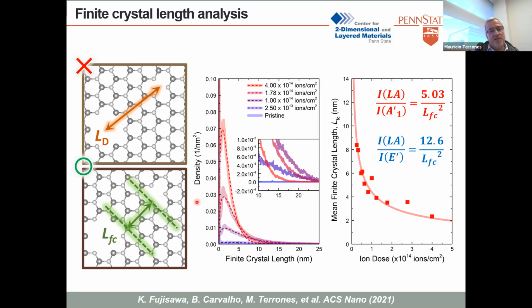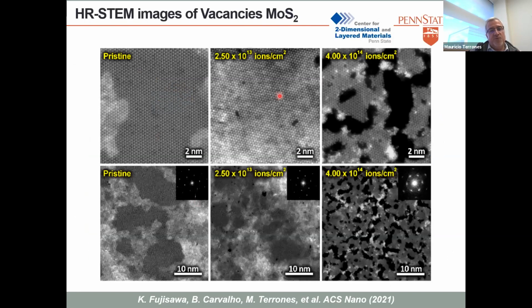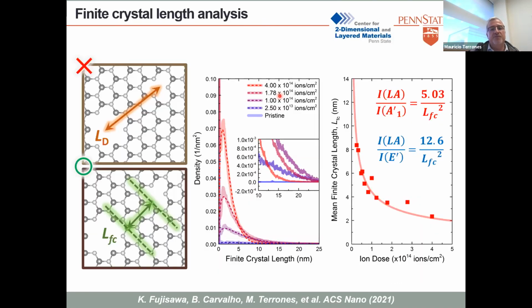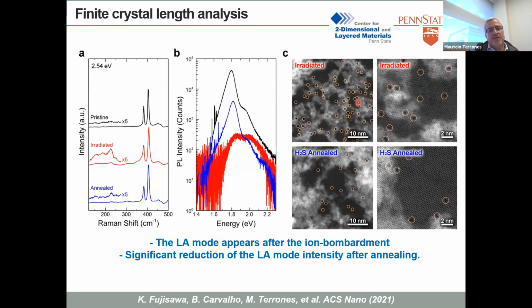So one thing that we did as well is that, once you have these defects, can you heal the sulfur defects? Can you reconstruct the sulfur defects? And the answer is yes, partially. If you do H2S annealing of this system, you start to fill the sulfur defects with sulfur atoms, and you can see here the photoluminescence: this is the pristine, and after irradiation there's almost no signal, but after annealing it sort of recovers. It doesn't come back to the same, but it recovers somehow. Okay, so I think that's a nice thing that we can do.